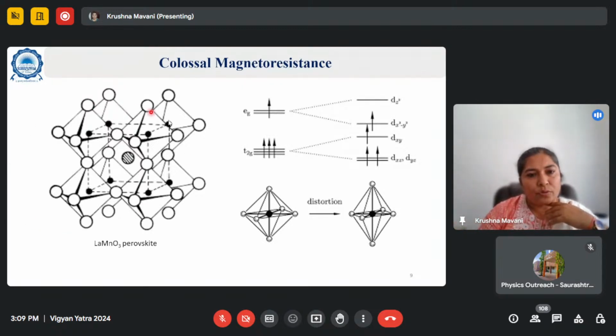So here I have shown you one ideal structure of LaMnO3 type of manganite perovskite, where you have lanthanum in the center. These are manganese ions, okay, and these are oxygen ions. So you can see one octahedral forming here in the single crystal. If a single crystal unit cell is given, you can understand this oxygen is also part of another unit cell on top of it. So that is why this chemical stoichiometry looks like LaMnO3.